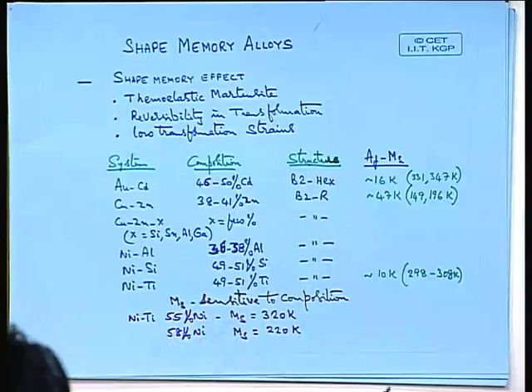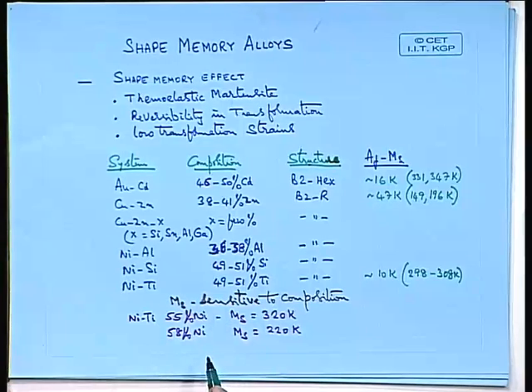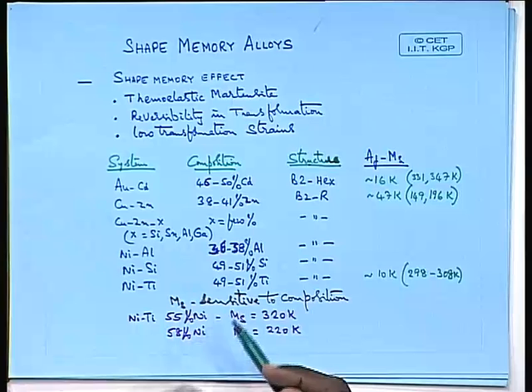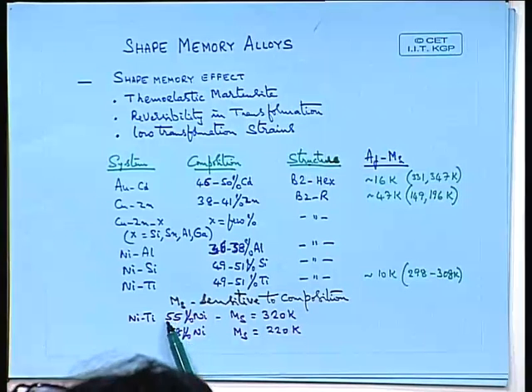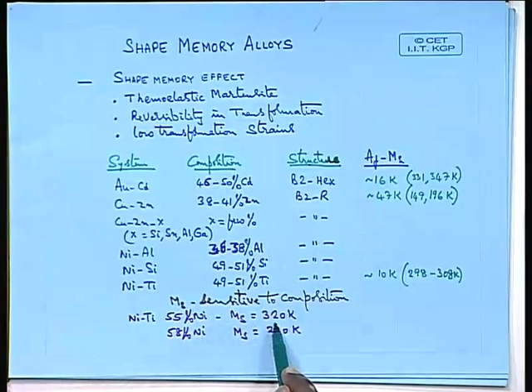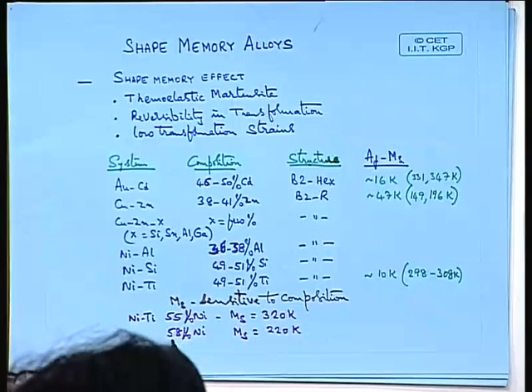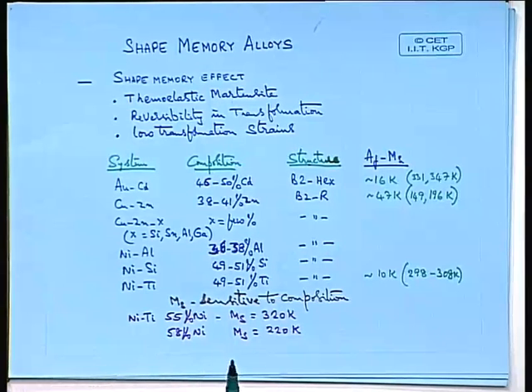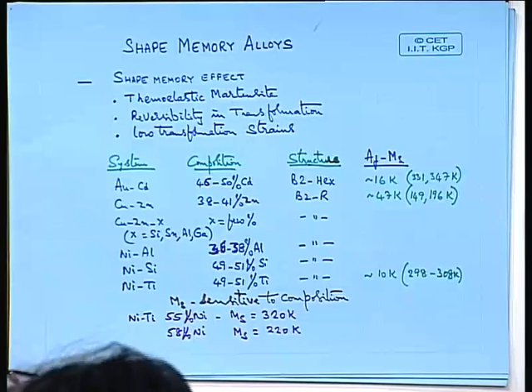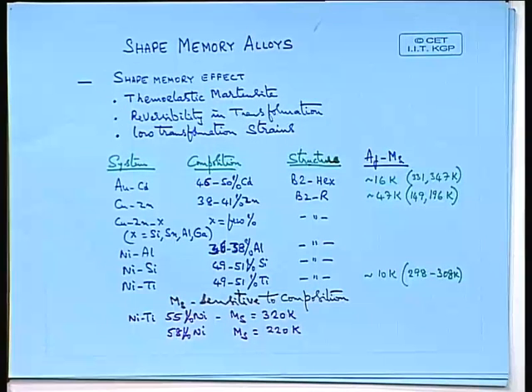But what is important is this is quite sensitive to temperature. If you look at titanium nickel, if you change the composition, the MS temperature drastically changes. If you take about 55% nickel, the MS temperature is about 320 Kelvin. If you take about 58%, just increase the concentration by 3% nickel, you will see the MS temperature falls to about 220, almost 100 degrees. So these temperatures are very sensitive to the composition of the alloy. So one has to consider the composition very carefully.